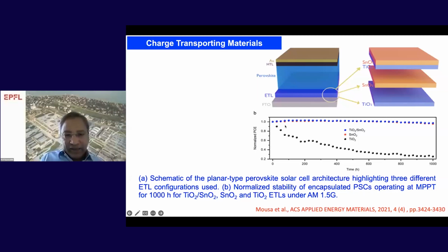Now, if you look at the efficiency and the stability data of this metal oxide ETL layer, with pure TiO2 the efficiency is decreasing significantly up to 1,000 hours. On the contrary, pure tin oxide, that's the red curve, which is merged with the blue dots. The blue dots are TiO2 followed by tin oxide.